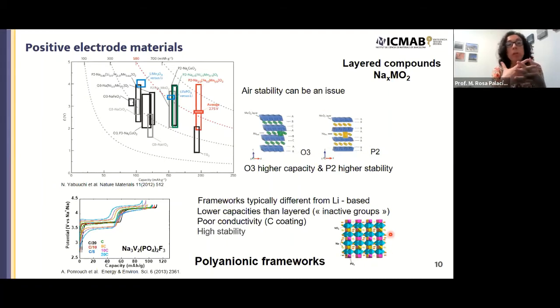the crystal structures are different from those existing in the lithium-ion technology as a result of this 3D character, because the coordination sites depend on the radius of the ion, and lithium and sodium have different radii. But still, this is one of the materials which has been successfully used as positive electrode material for sodium-ion batteries: sodium vanadium fluorophosphate. And there are French groups, Christian Masquelier and Laurence Croguennec, that have worked a lot with this compound.